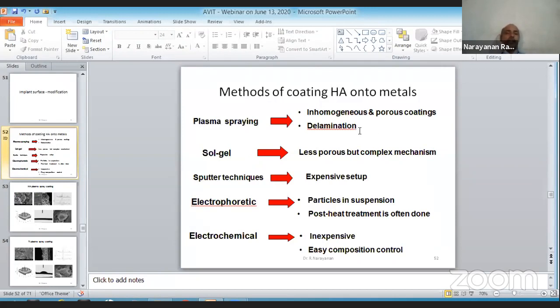But there are certain problems. Probably there will be uniformity, but it is generally porous. Whether it is good or bad is again a debatable issue, and it can form a lot of volume. I mean, thickness will be high, but the outer layers tend to come out. So there's something called delamination. Layer by layer removal is possible. So it's called delamination. Plasma spraying is generally acceptable for uniform coating commercially, not only for medical grade, even for engineering grade coatings. But there are a few problems, but I think overall plasma spraying will be better.